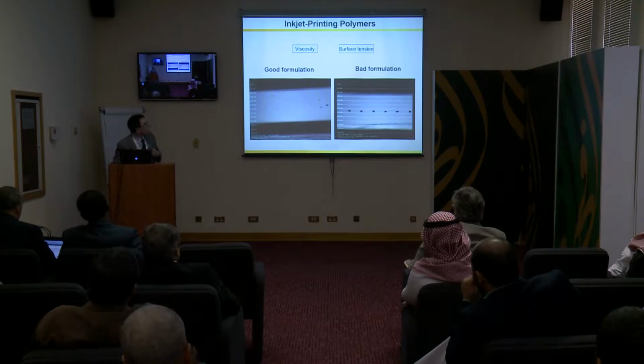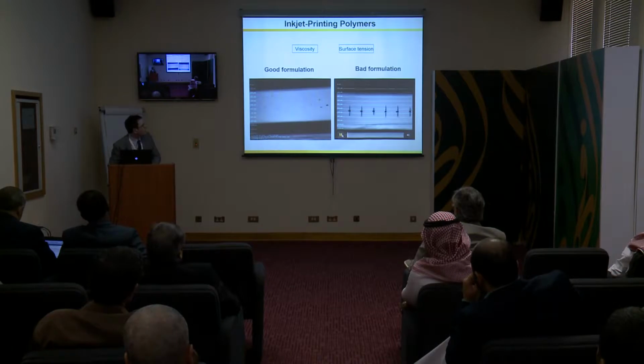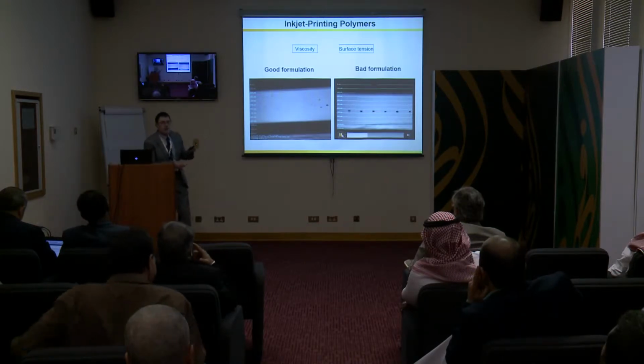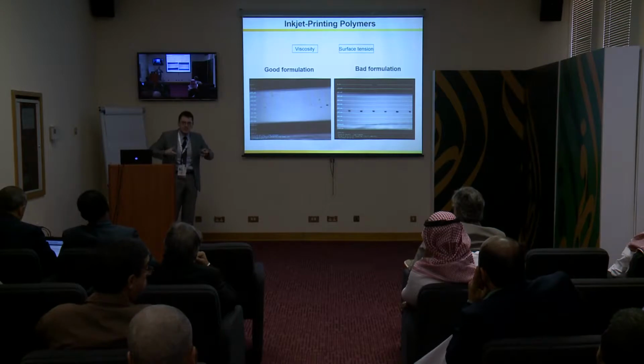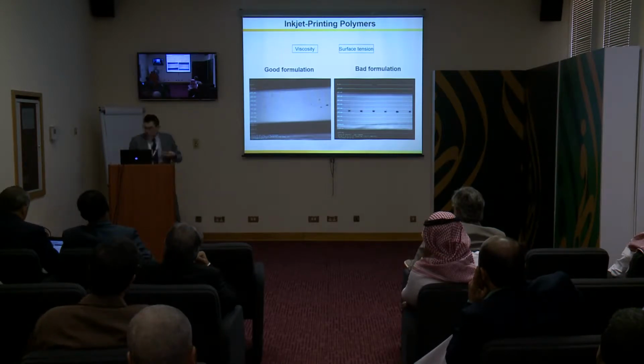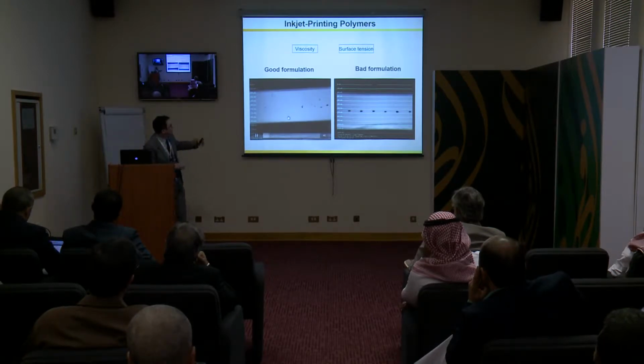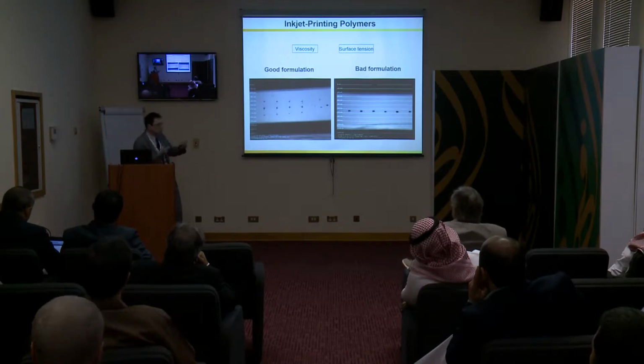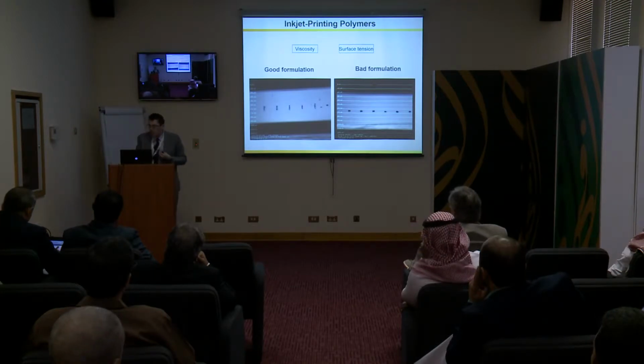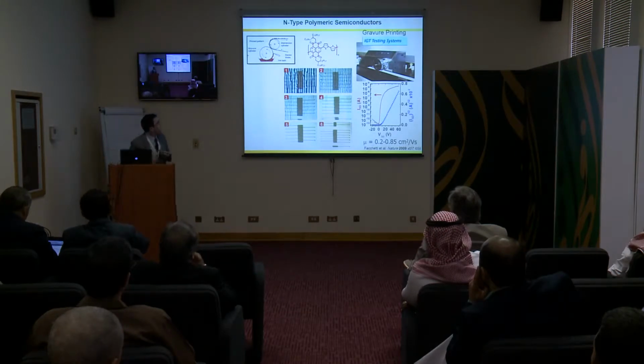We have done work to try to develop inkjet printable polymeric formulation, and what you usually end up with is something which looks like that. Because of the rheological property of the polymer, it's very difficult to eject it. So we've done quite an amount of chemistry in trying to optimize the polymer architecture, and usually by changing the end functionality or changing the molecular weights to enable inkjet printable semiconducting polymer for these applications. Another way to print is called gravure printing, and this is very different.